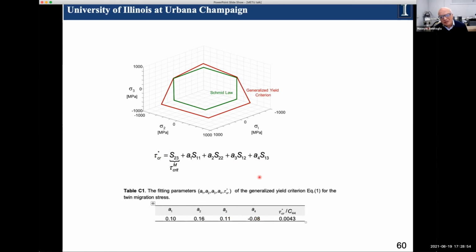And this is mostly the work that Sertan Alkan did 3 years ago. And we are obtaining these generalized yield criteria now almost. It's the case with BCC, of course, because we already know there are partial dislocations on multiple planes. So the stress state is not dictated by a single plane; it's dictated by the shear on other systems, right? But also normal stresses have an effect.